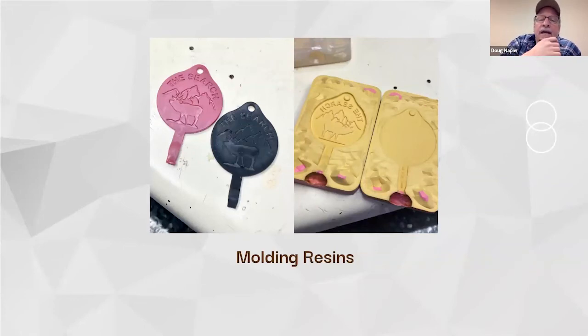Here's another way that I get around that. There are some pieces that have a lot of lettering, and it might take 3 or 4 or 5 times of casting before you get a good one. What I've done in the past is I'll take the rigid resin and print it out with a sprue on it and make a Castaldo mold out of it. It'll survive the heat because, when you make a mold, it's only 300 degrees. This resin doesn't break down till about 700. So I will actually make a mold of some of these finer pieces and then inject the wax and cast the wax. It's just one way that you can get around having to try and cast a big piece with a lot of lettering over and over.